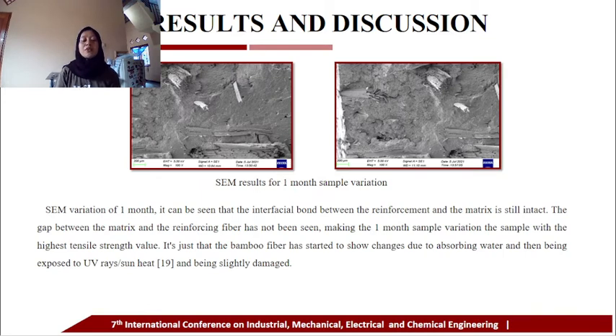In the 1-month variation, it can be seen that the interfacial bond between the reinforcement and the matrix is still intact. The gap between the matrix and the reinforcing fiber has not been seen, making the 1-month sample variation the sample with the highest tensile strength value. It's just that the bamboo fiber has started to show change due to absorbing water and then being exposed to UV rays or sun heat and being slightly damaged.